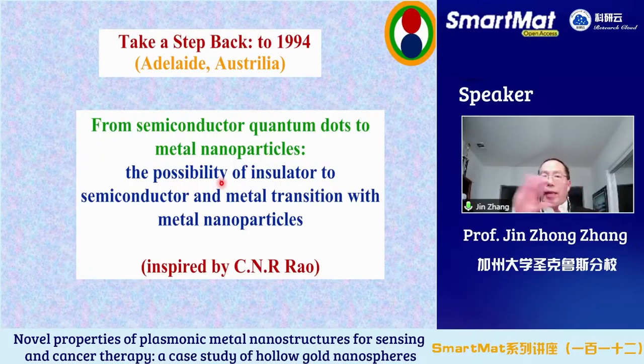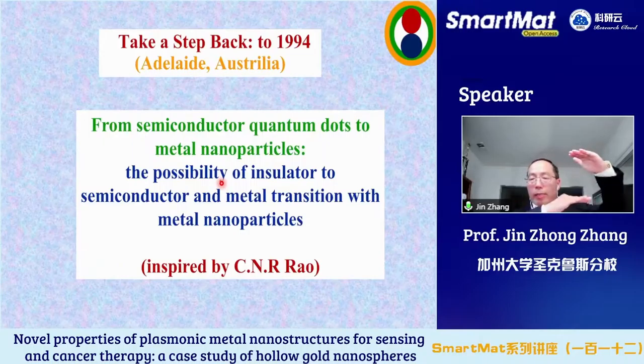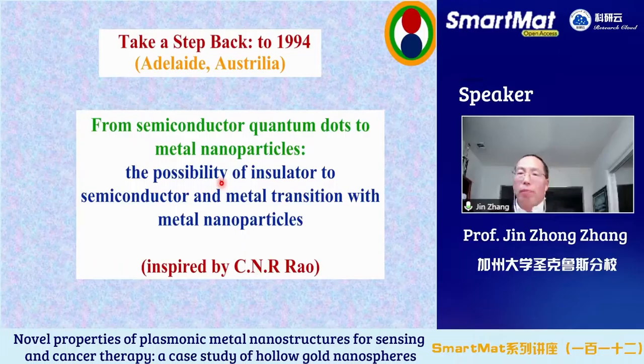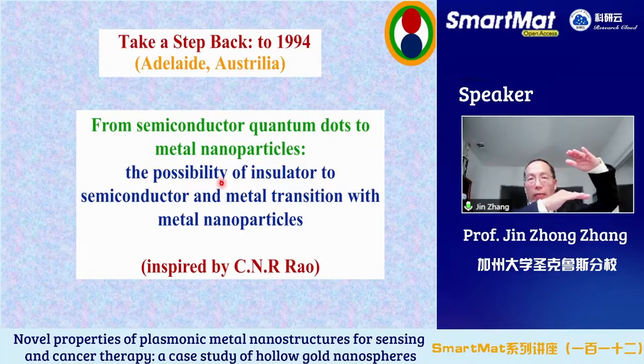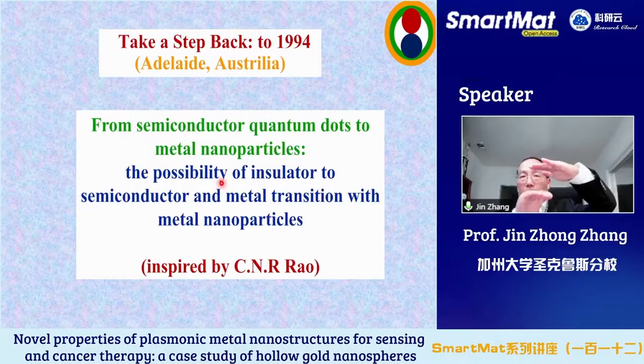If you remember the energy diagram I showed you earlier, when you go from small to large, the band gap becomes smaller. At first, the energy spacing is large. When the size becomes larger, the energy spacing becomes smaller. If it's a metal, it becomes so small that it becomes zero. That's a metal. So you initially have an insulator with a single atom. With a cluster or nanoparticle, essentially you have a semiconductor. Then for metal, eventually the conduction and valence bands overlap. So that's a metal. So yes, in principle, he's exactly right.